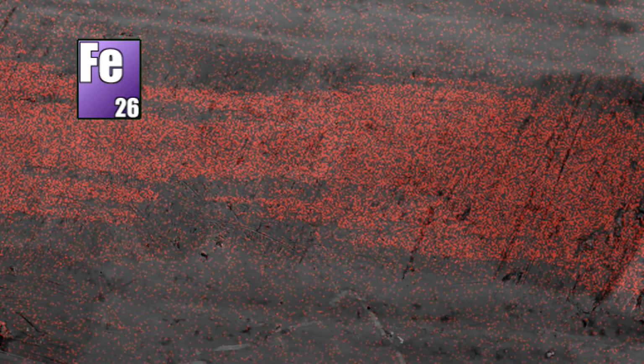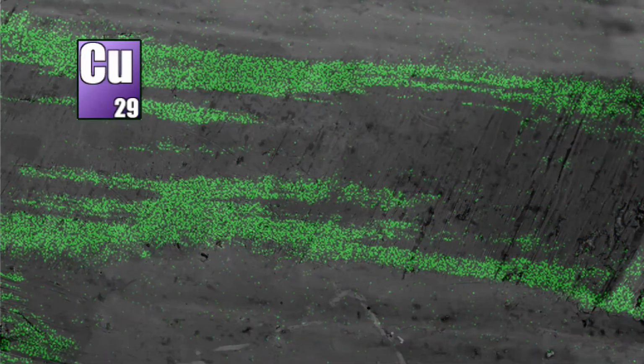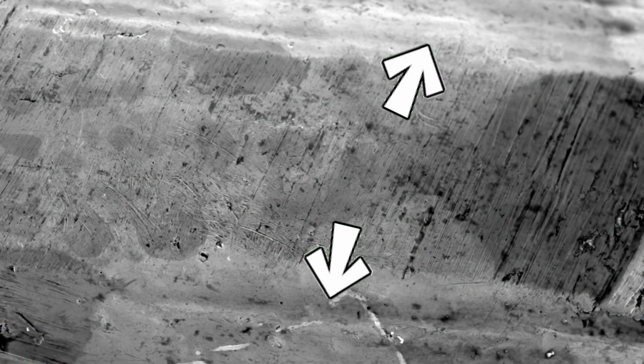Okay, so here's our area that we sanded, and we can see a lot of iron here, which means we sanded all the way through any layers on the surface. Good. We can also see copper still here on the top of the iron and a little bit around the edges of where we sanded the area, which is what we would expect. But we haven't seen anything showing up too much in these areas that weren't sanded. So whatever element or elements we see here will be the mystery silver colored layer.